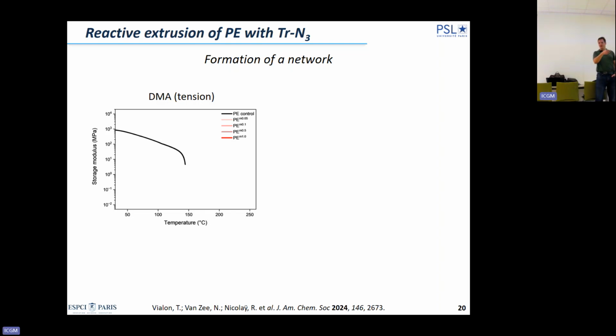So if you do DMA, dynamic mechanical analysis, here you have the storage modulus, or elastic modulus, because it was in elongation, so not storage. Temperature: our starting HDPE, as you would expect, when you are close to the melting temperature, in our case slightly above, with the delay, the material flows under its own weight, and you can no longer measure an elastic modulus.